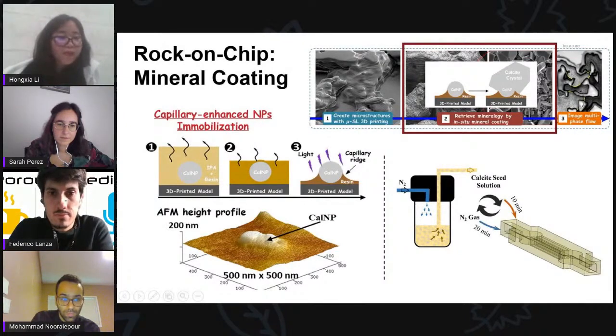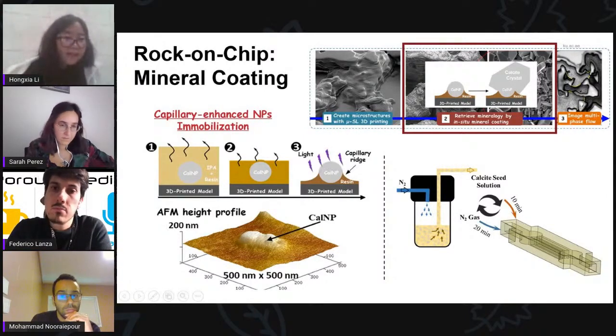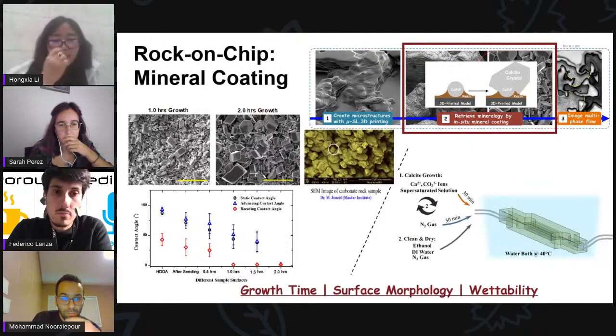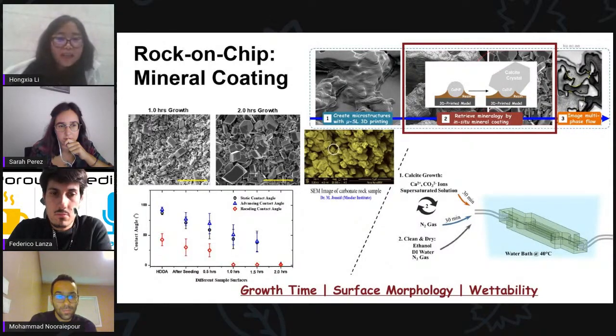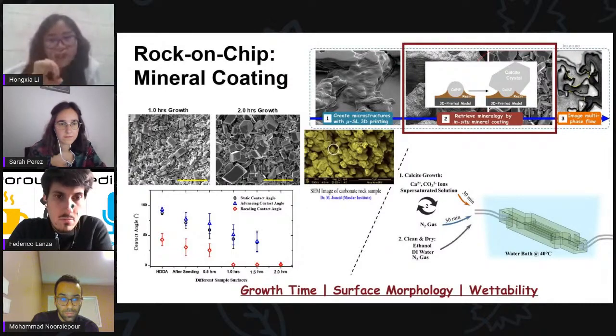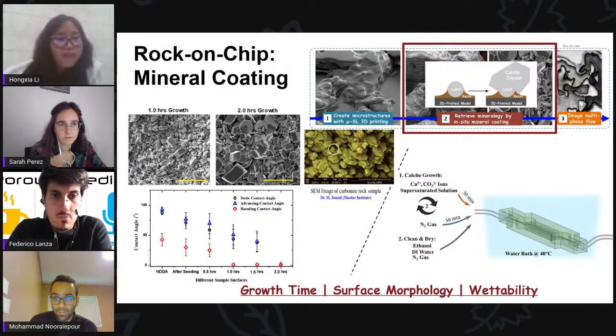This is also confirmed by an AFM height profile, that is atomic force microscopy. We can see the nanoparticle is fixed on the surface, and around it there is some capillary ridge, which helps increase the contact surface to fix the particle. Then with those seeds, we can further grow the crystals. To do that, we immerse the whole device, the chip, into a water bath at 40 degrees C, and we inject the saturated ion solutions. With the temperature change, these solutions become supersaturated, and then start to grow on the seeds we fixed previously. By controlling the growing time, we can control the crystal size.